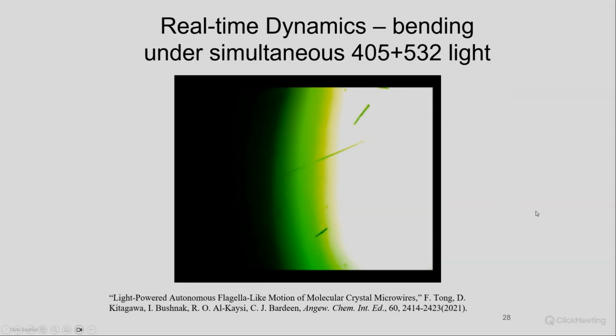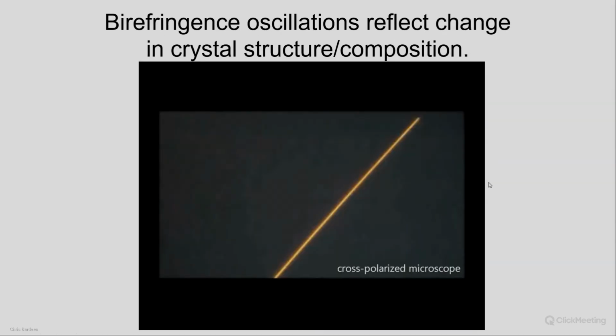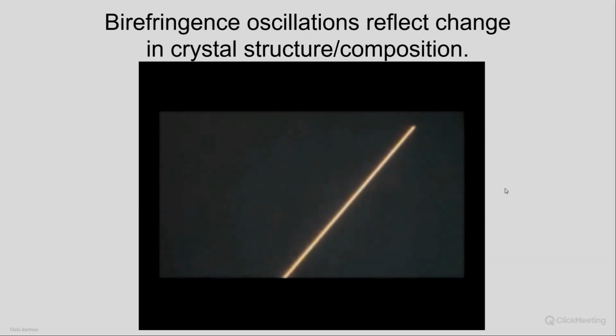And you can also confirm that this corresponds to a change in the crystal structure. This is a birefringence image of a very similar crystal, not the same crystal. This is also a microwire. And what you can see is, the crystal is not oscillating as dramatically as the previous one, but the birefringence is also changing in an oscillatory manner because the crystal structure is changing, because you're getting more E versus Z as you cycle back and forth. And again, you have to have some sort of ability of mechanical motion to couple the light absorption with the chemical changes happening inside the crystal.